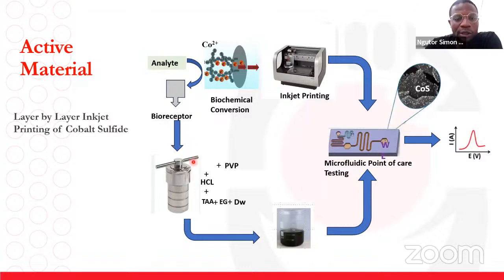We mostly print on polyimide. There are different substrates, but here in our lab we basically use polyimide because most of the materials we work with sometimes need higher temperature treatment, like for graphene, which sometimes needs 350 degrees to make it conductive on the polyimide. We need a substrate that can stand that temperature range.